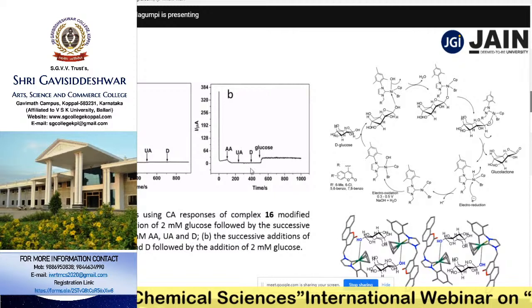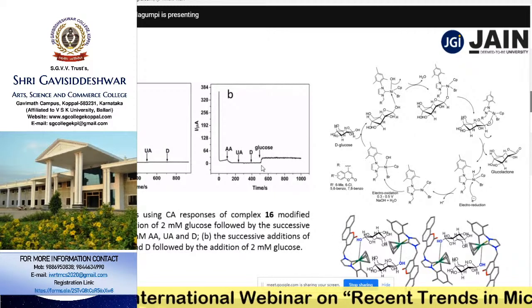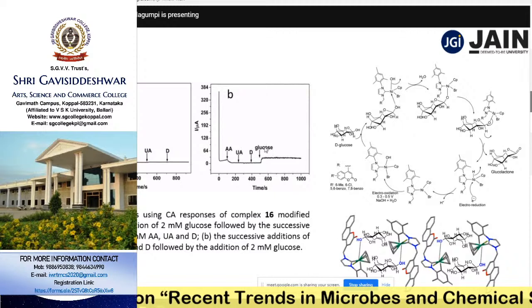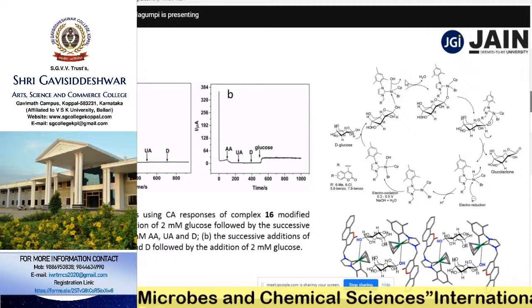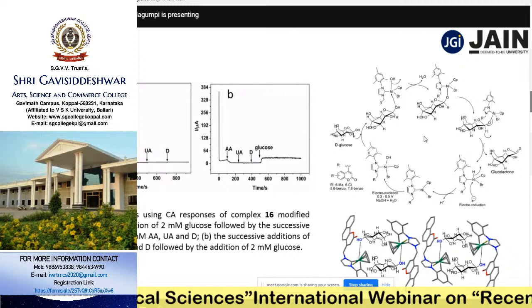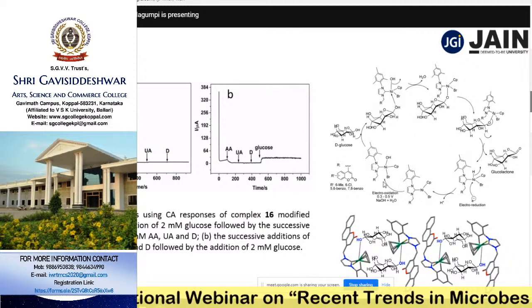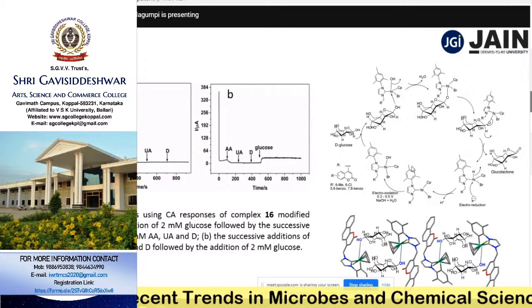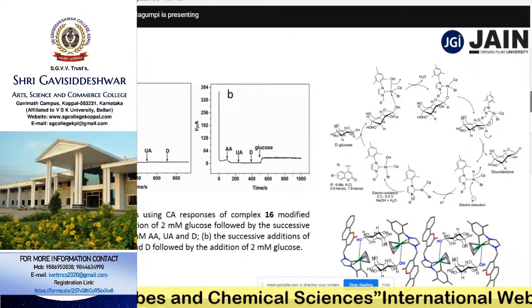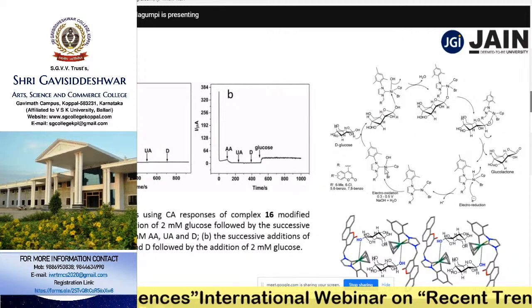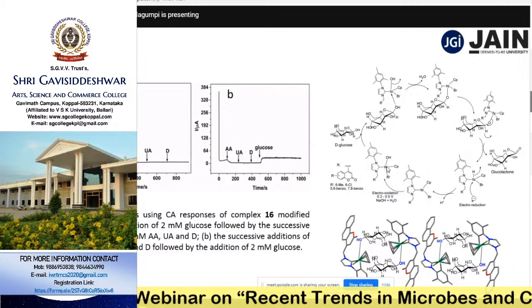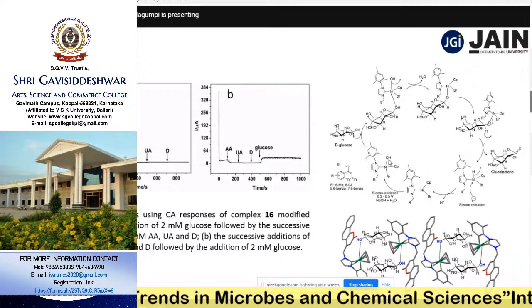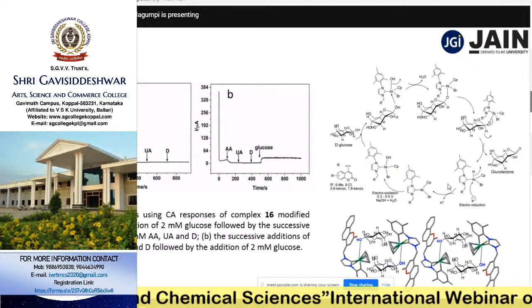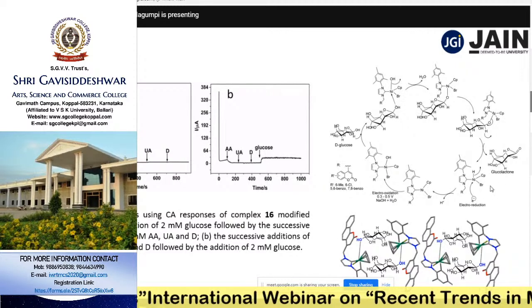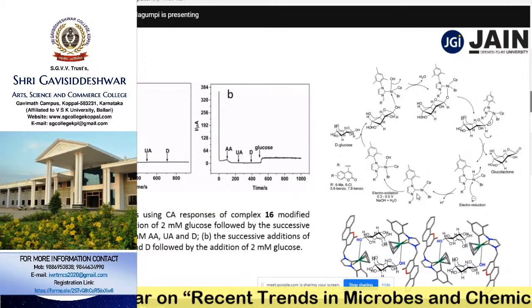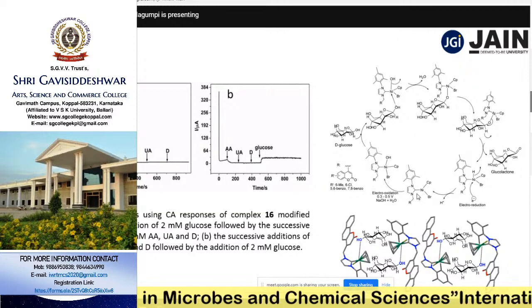There is an increase in the current response that indicates that these complexes can selectively bind to glucose or selectively identify the glucose. So on these grounds, we have just predicted the plausible mechanism of how glucose is sensed by these molecules. This is through the oxidation and reduction process. This is the complex which is modified on the glassy carbon electrode. Nickel 2 undergoes oxidation to form nickel 3 with a hydroxyl species. So this enters the catalytic cycle, and again glucose is oxidized to glucolactone, while nickel is reduced to nickel 2. So this is the possible mechanism.